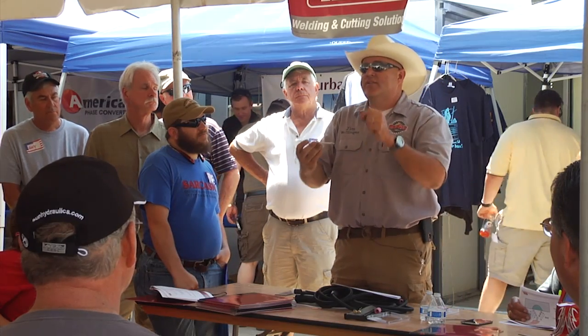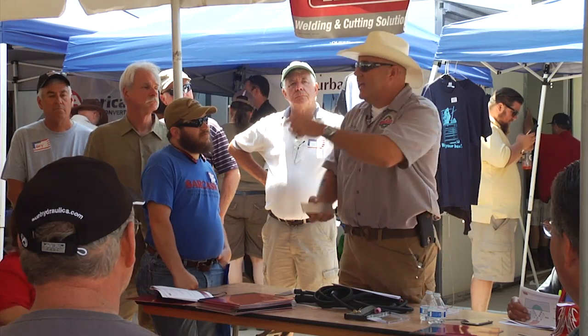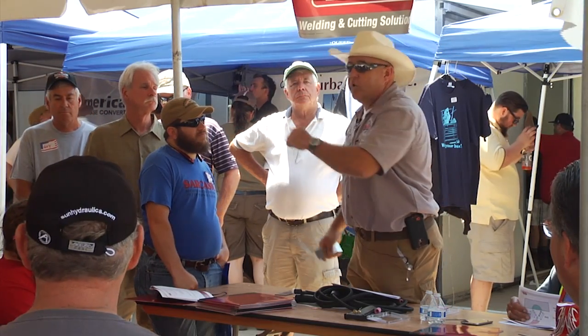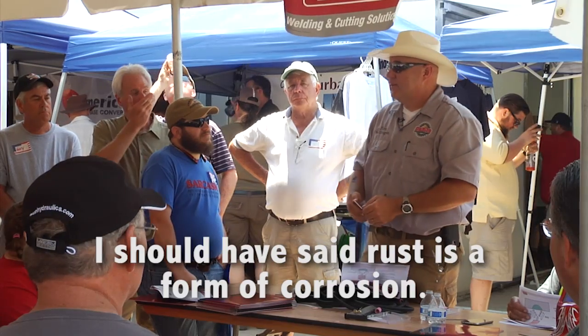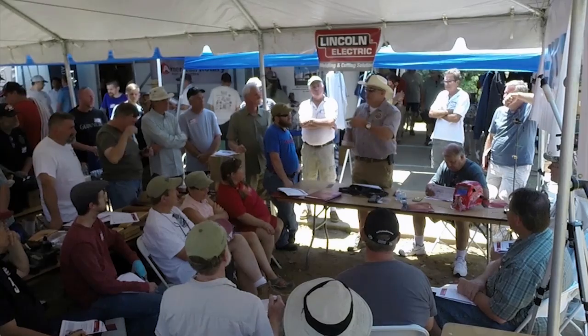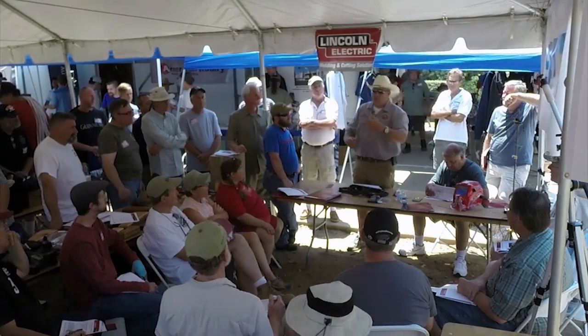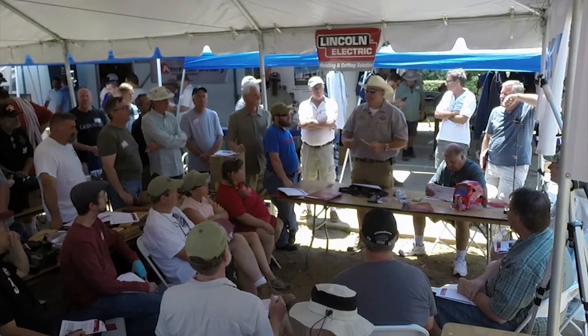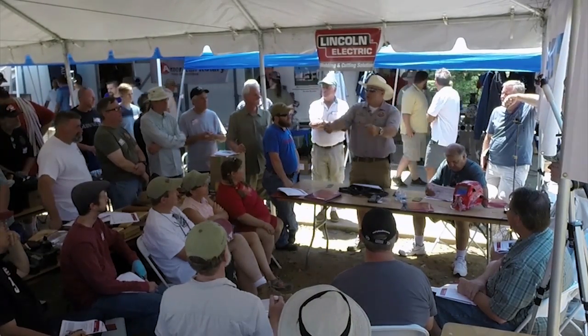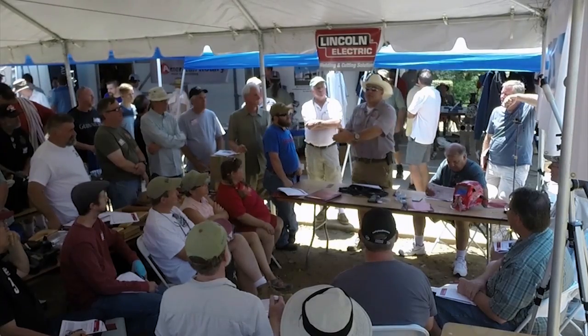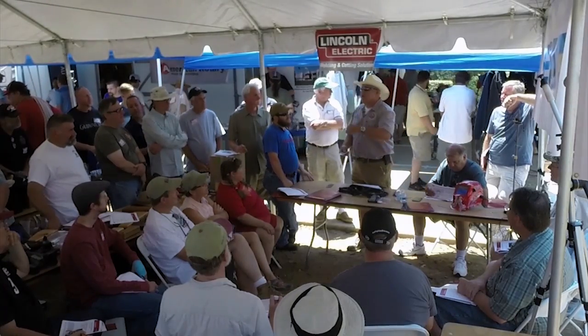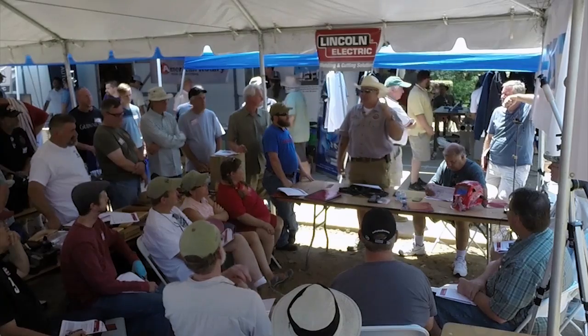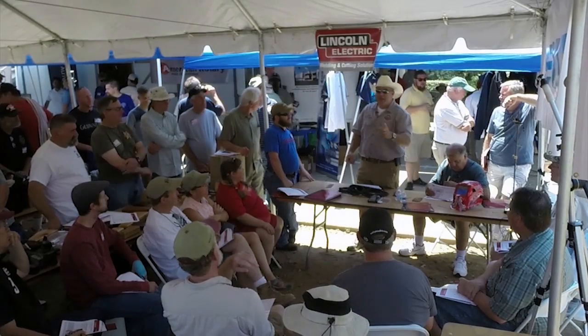Almost instantaneously in our atmosphere, aluminum oxide forms back over the top of the aluminum, which keeps it from corroding, but yes, corrosion is a form of rust. So it's self-healing. That's why we like them for boat tops, and we have a lot of that in Florida, boat tops, lawn furniture, because if you drag it across the concrete and scratch off the aluminum oxide, it begins to heal almost immediately behind itself. It's like your own can of Krylon, right? When you have to paint it.